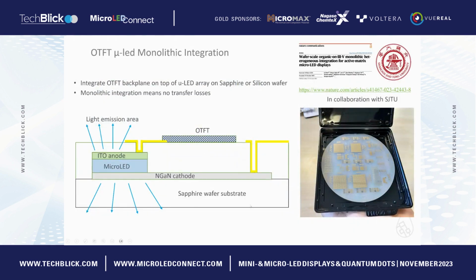So the way we've thought of doing this is say, can we not move the LEDs at all, just leave them on the original wafer? So what we've done is to apply a planarizing layer so that we can create a sputtered contact down to the via of the anode and the cathode of the LED, and then process the OTFT on top. And that way we can use compatible processes for backplane manufacturing of photolithography, dry etching or direct patterning, and sputtering for the metals.